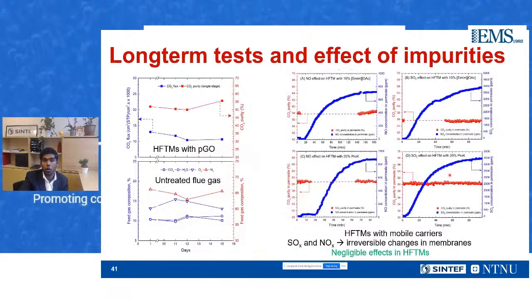So we also subject these materials to 14-day testing without any disturbance. So a continuous exposure to the flue gas. Please note that these flue gas was not treated, which means they are raw flue gas with impurities present in it. And when this was exposed for 14-day operation, there was no drop in CO2 flux or the permeability or the purity, and it was recorded to be quite stable. The performance from the SOx and NOx exposure also showed that when we expose it to SOx and NOx with a very high concentration, we never saw a drop in performance of CO2 purity.